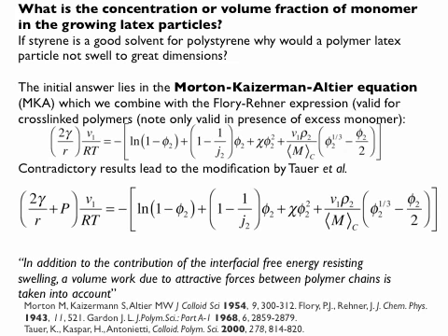Now the left-hand side has a little bit of what you might recognize, which we saw in the first or the second lecture. There's a Laplace pressure term in there. This only holds for a sphere: 2 times the interfacial tension divided by the radius of the particle that is swelling. If you would derive that term, it's basically the Gibbs-Thomson relationship.